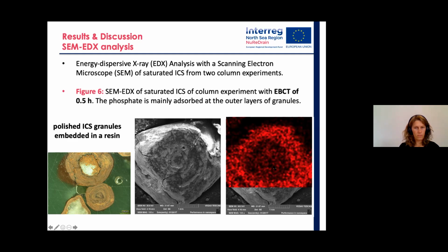And what you can see is in the center you have some phosphorus adsorbed, but the most part of the phosphorus is adsorbed at the surface, the outer surface of the granule. That was the conclusion that we took from these images.